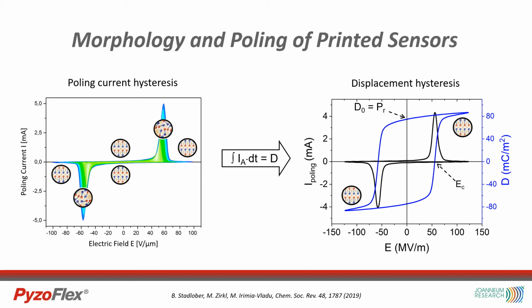This chain rotation produces a poling current that peaks at the opposing coercive fields. By integration of the area-normalized poling current curve, shown here, we get the displacement hysteresis loop. It shows the typical bistable nature of the ferroelectric polarization.